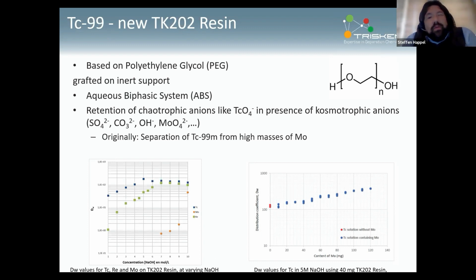What is quite particular, and where we feel that there might be a good application, is that you need to work in quite high hydroxide concentration. So if you see the graph on the lower left, working at 5, 6, 7 molar sodium hydroxide will allow you to extract technetium and rhenium very strongly, amongst others from dilution. And again, if you are in the presence of other water structuring anions, in this case molybdate, you will find that adding more matrix, more of these water structuring anions, you will increase the retention of the technetium. So overall, that feels like a system that might be quite useful for the analysis of samples that do have quite a lot of anions of matrix charge.